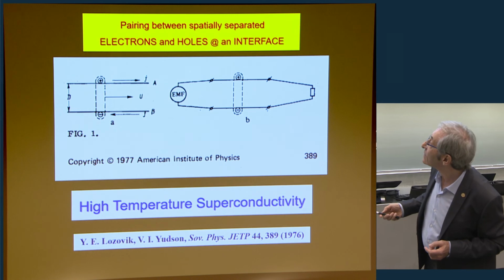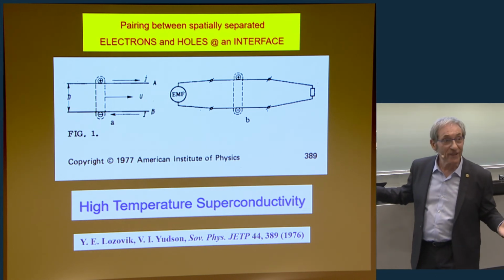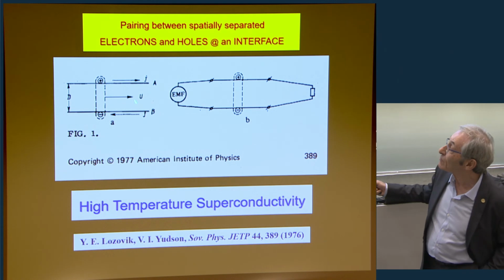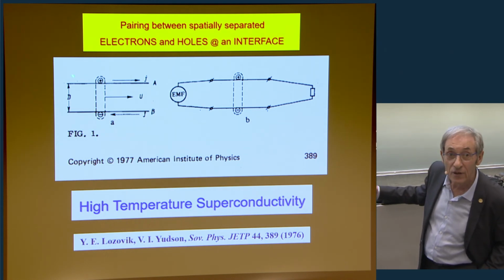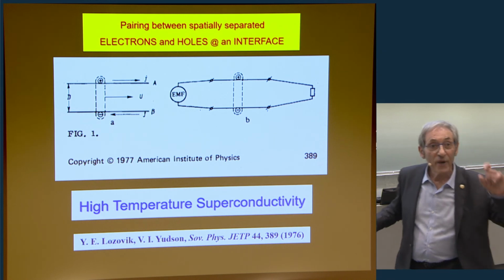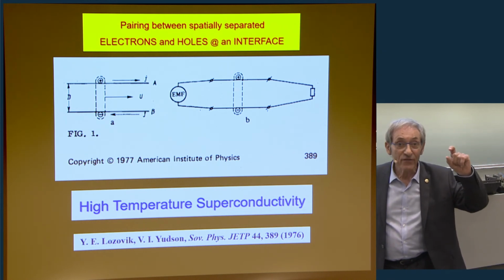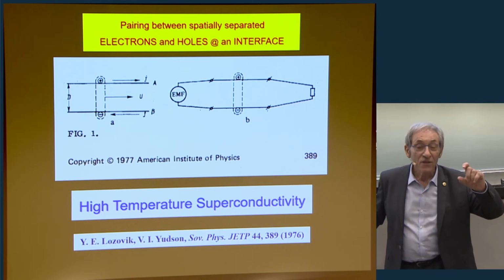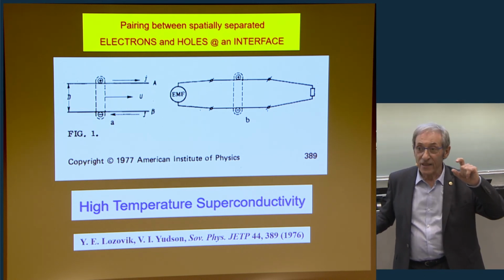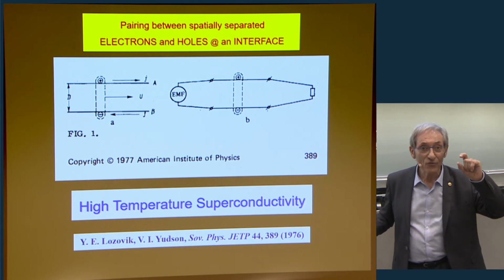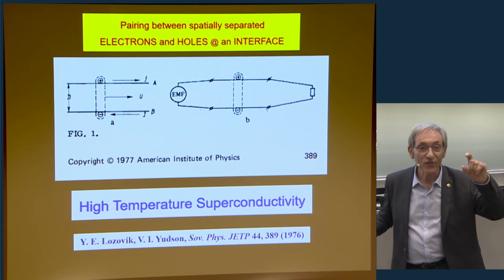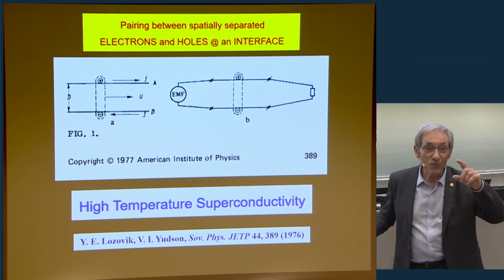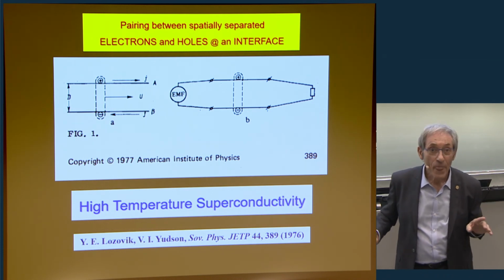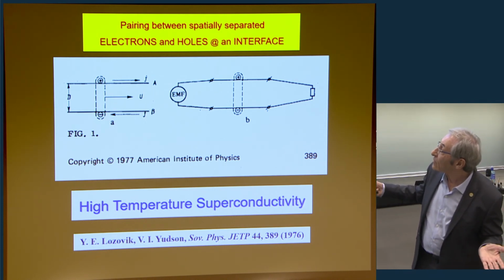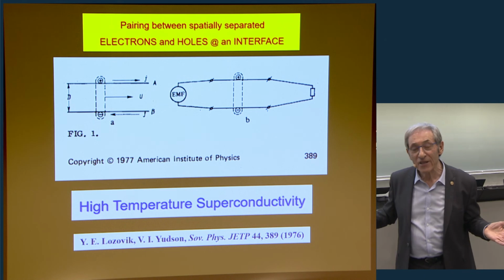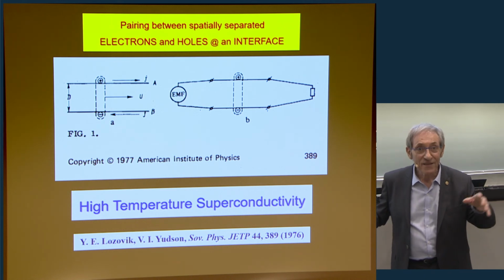And also predicting high temperature superconductivity, here you must have an electron and a hole moving together, separated by a thin insulator that prevents tunneling between the two. So what we have on the silicon is a thin layer of silicon oxide, about 1 to 2 nanometers, and our monolayer, about 2.6 nanometers. On top, we have silver, and underneath, we have holes. So it also looks like this, although in our case, we have much more surprising results, which are not predicted by the theory.